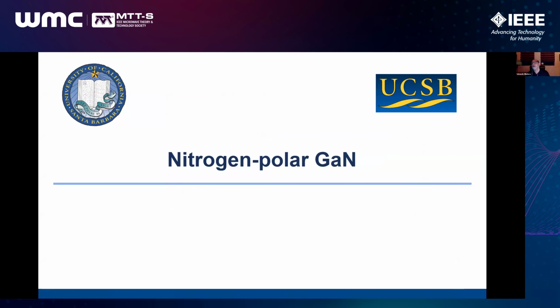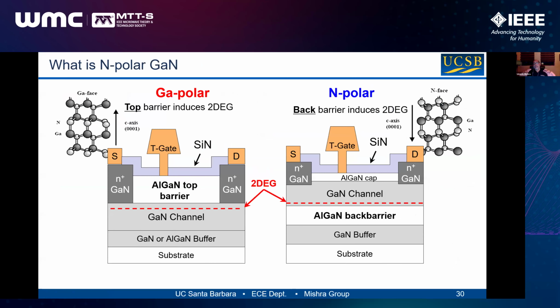Tremendous amount of research. What we chose to do at Santa Barbara is nitrogen polar. And what we did was just flip the material on its side. So instead of having AlGaN on top of GaN, if you look down on gallium nitride, you'll see gallium. And just below that, a few angstroms below that, is nitrogen. If you flip it, you'll get nitrogen on the top and a few angstroms below that, gallium. So it's not a symmetric system. You turn silicon, you get the same thing. You turn gallium nitride, you get exactly the opposite. It's a huge difference, okay?